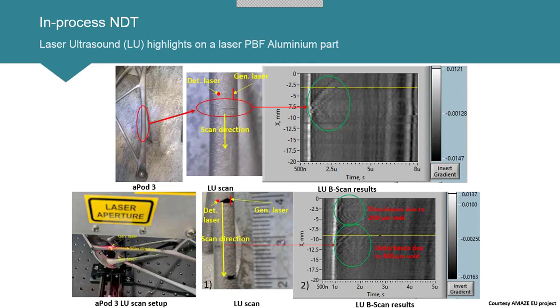Then just a couple of slides on in-process NDT, which was developed during the AMAZE project. This is the same part that Donna showed, and it's called aPod 3, but it's the Thales part. This is an aluminum part which was built, but in this case, it's showing the process was not under control, which in some way is good for NDT, because we like to see defects and then test if the NDT method is capable.